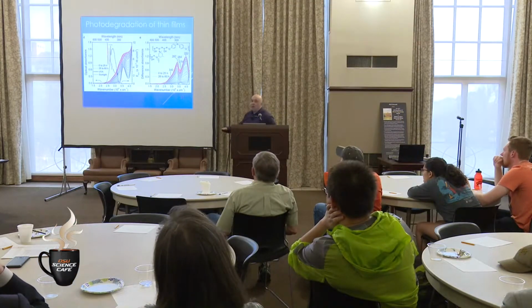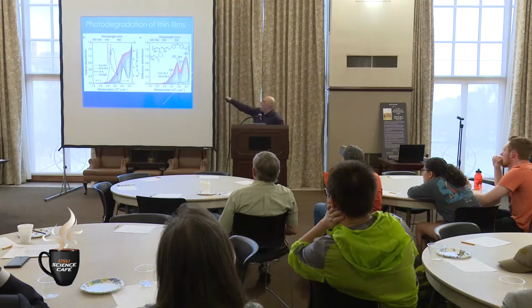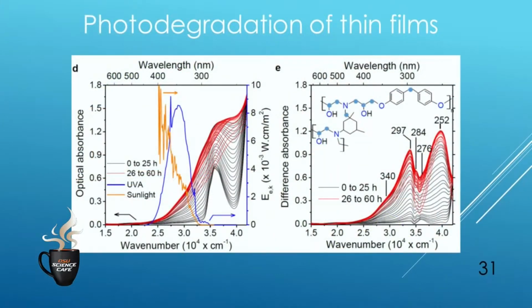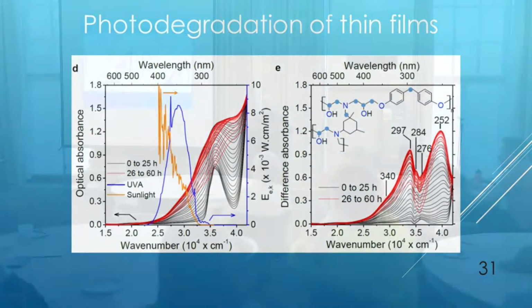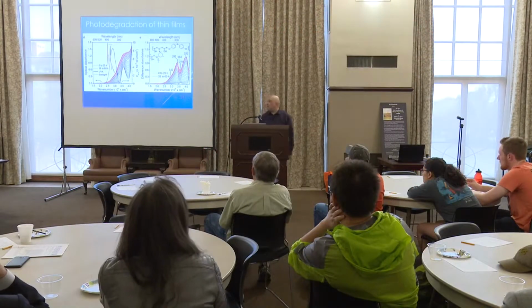So this was actually epoxy, and there are different sites which can be oxidized by oxygen. So these blue little buttons will turn to all carbonyls. And they have different carbonyl bands. You see a peak at 340, peak at 297, 284, 276. So a bunch of carbonyls. By the way, this spectrum is a different spectrum. This spectrum shows what change is happening there. And significant change is really happening. But what we were claiming is that the way that change is happening is due to the carbonyls.